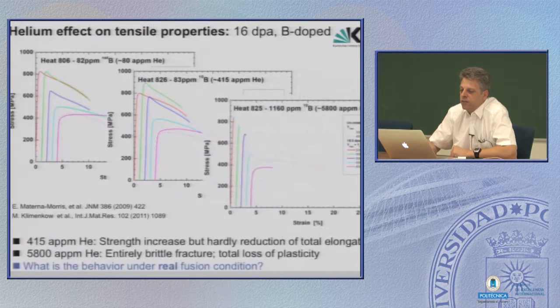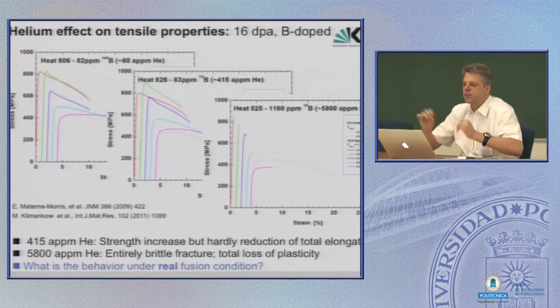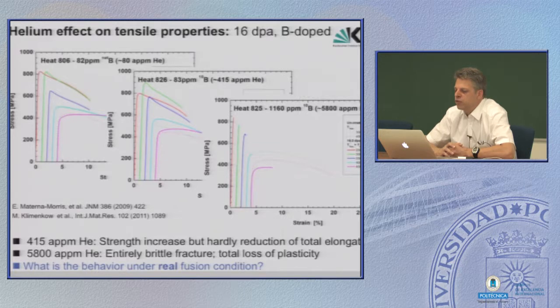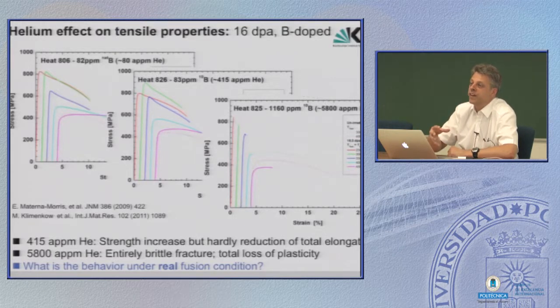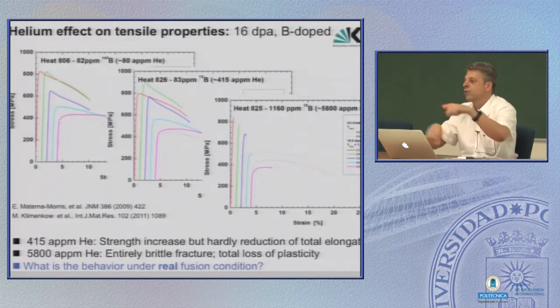With increasing helium amount, as you see here, there is ongoing hardening, loss of ductility, and finally, in the range of 1000 appm helium, the steel is completely brittle and totally useless. Now there are two possibilities. One says that this artificial helium production is an overestimation of reality, since in a real neutron spectrum in a fusion device, the helium distribution is more uniform and doesn't lead to such severe bubble formation. But nobody knows, since we cannot irradiate material exactly with the environment in a fusion reactor. For that, we would need a fusion reactor, but in order to build a fusion reactor, we first need to have the data. So what can you do?